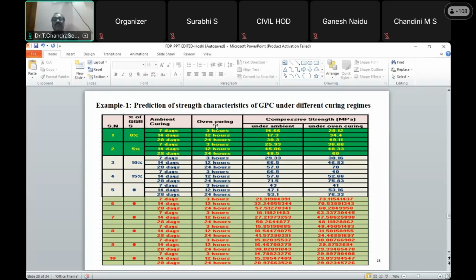But another one is the fast and quick one. Actually, the concept was developed based on oven curing in Australia. The concrete specimens are kept in an oven and heated to 60 to 100 degrees, varying the temperature.